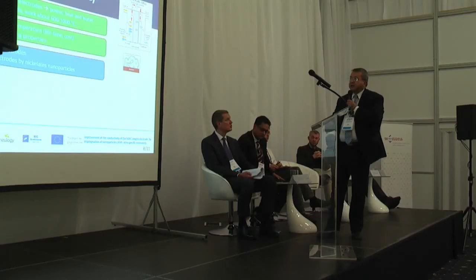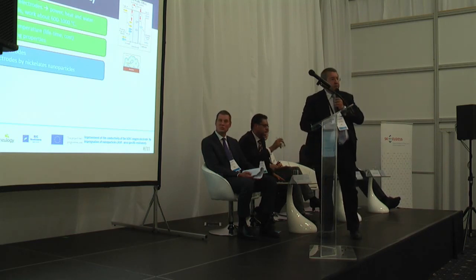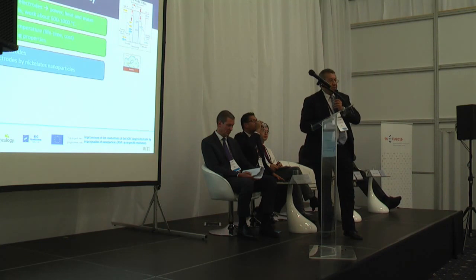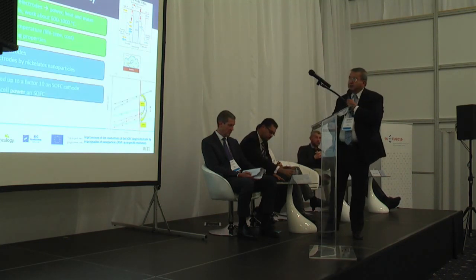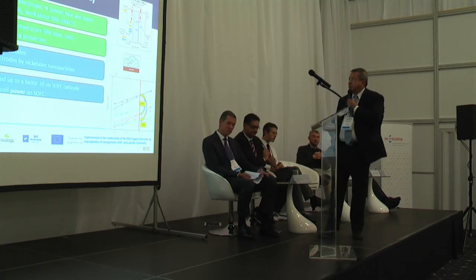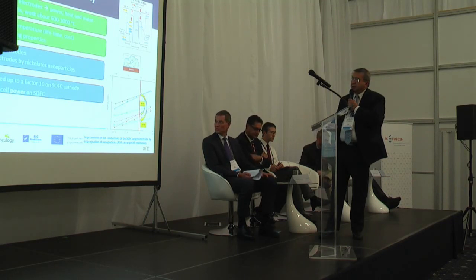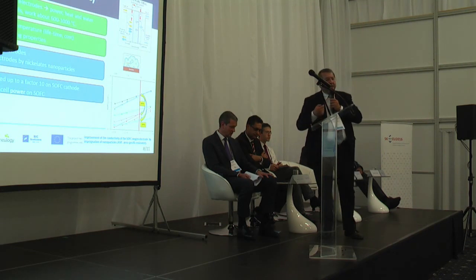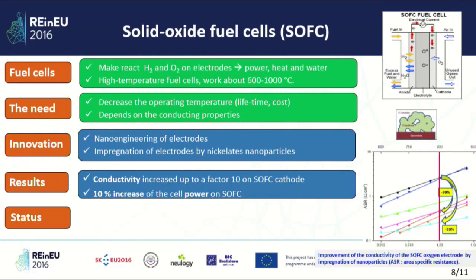It's more or less a kind of impregnation of electrodes by nickel nanoparticles. That's not so easy, with very numerous parameters, but in the end, we demonstrated that you can increase the conductivity of the cathode by a factor of 10.